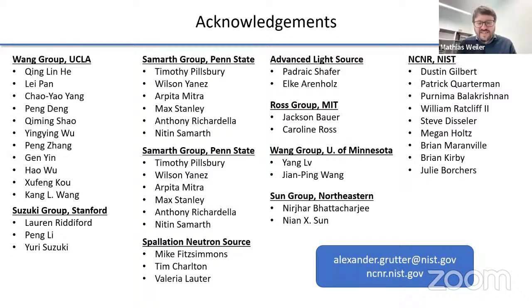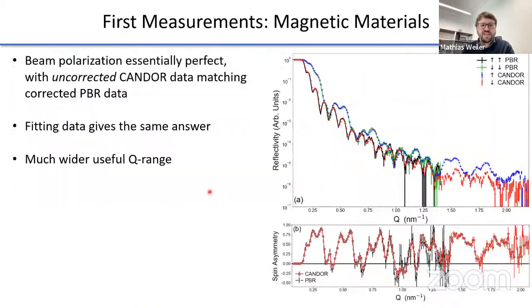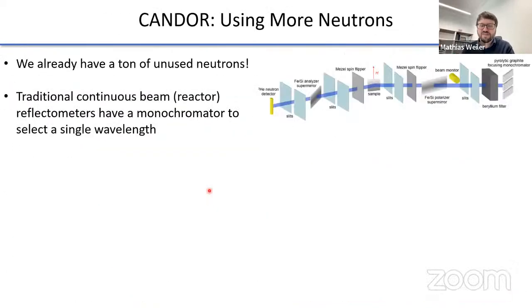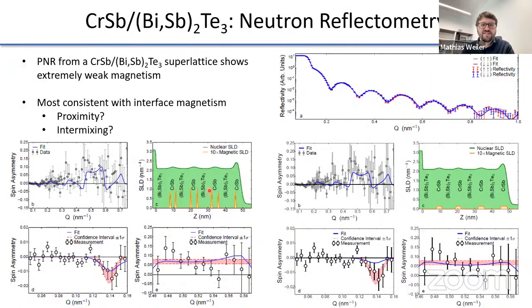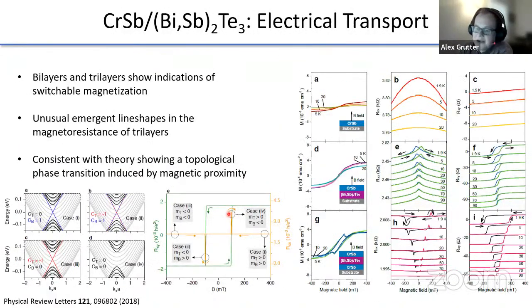Yes, thank you. First of all, thank you for the great talk. It might just be a minor detail, but one thing you talked about was the chromium antimonide on top of the topological insulator. And I think that is now known to actually be an altermagnet and not an antiferromagnet. Sorry, I missed a little bit of that. It's known to be a what? An altermagnet. So it's like an antiferromagnet that has a spin polarization. Does that somehow change the interpretation of electrical measurements like the anomalous Hall effect that you see in the system, or of this particular data set?